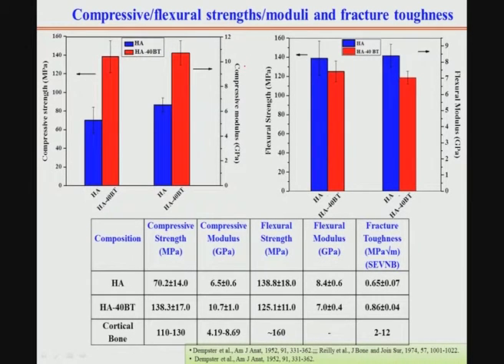Now, the compressive strength of these materials can go up to 138 megapascal, which is quite a respectable number in the ceramics community. Flexural strength is also more than 125 megapascal. Fracture toughness by SEVNB is low, it is less than 1 MPa square root meter.